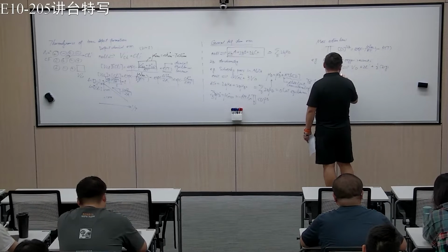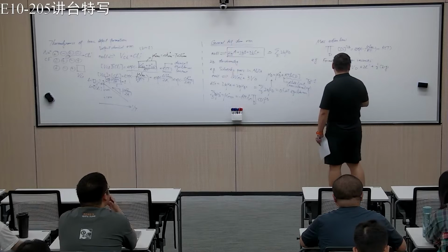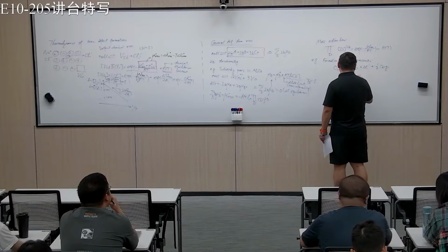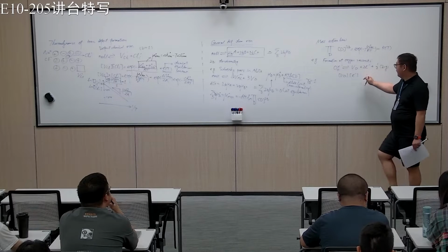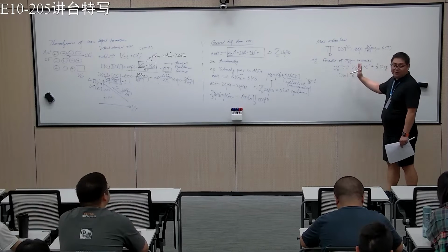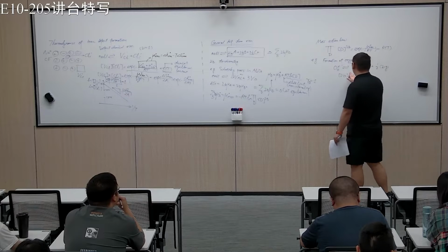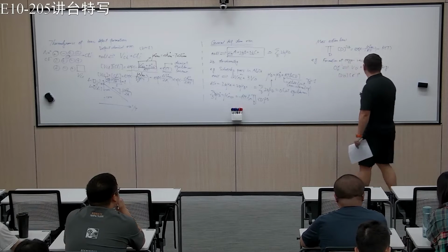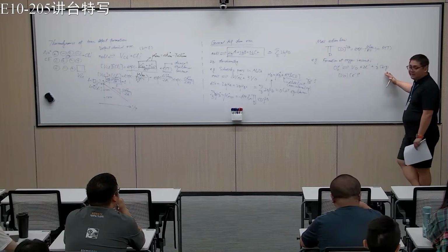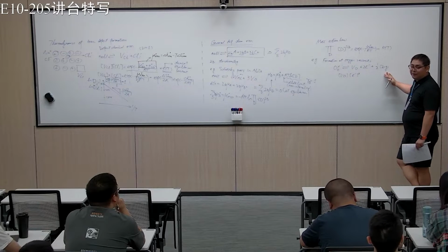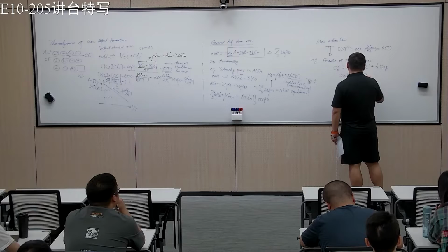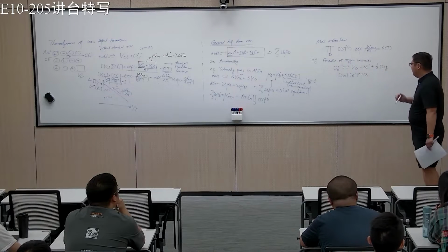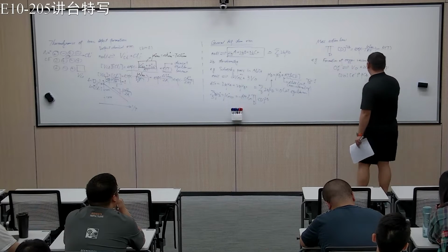So what you can write is oxygen vacancy fraction, then electron fraction. Of course, notice here we have 2, right? So there should be 1 here, but 1 you just neglect. So we have 2 here, and we have oxygen gas. For the gas phase we don't use the fraction, we use the pressure or partial pressure, right? Of course, there's 1/2 here, so we have to write 1/2.